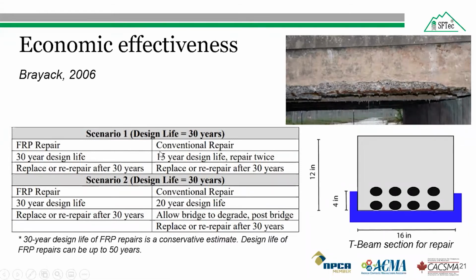In scenario 1, the conventional repair was designed for a service life of 15 years and should be repaired again after 15 years, so it will be repaired 2 times. In scenario 2, the conventional repair had a design life of 20 years and will be allowed to degrade after the 20 years, and after the completion of the 30 years, it will be either replaced or repaired. However, in both scenario 1 and scenario 2, FRP repair will serve for a conservative design life of 30 years. I'm saying conservative here because the FRP repair can have a design life of up to 50 years. Therefore, fiber reinforced polymer repair has a better design life than the conventional repair.